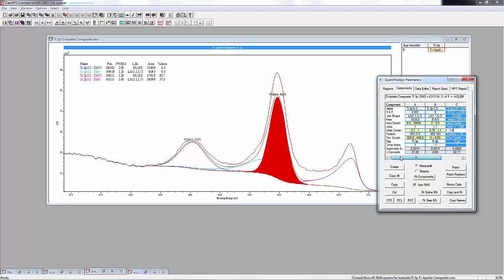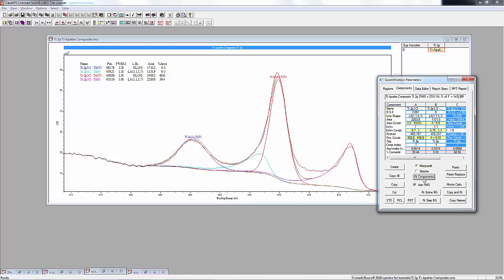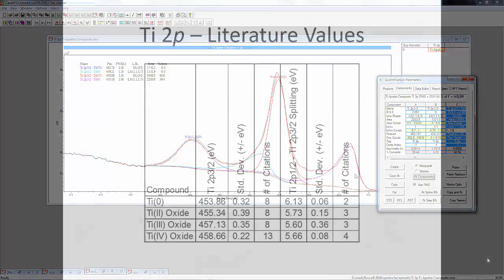The other thing that I've done is I've zeroed out the RSF value for the 1/2 peaks, and what that allows us to do is it gives us an easy quantification between just using the 3/2 peaks, so we know how much of each different species we have. Otherwise we'd have to add together the total of the 3/2 peak and the 1/2 peak, so that's a nice way of doing it. Let's hit fit. That's pretty good, but obviously we're missing some stuff here. Because we have the metal and the Ti4+, there's probably some suboxides in between - titanium 2+ and titanium 3+. So I'm going to fit in some peaks that correlate to that, and that's from literature values.